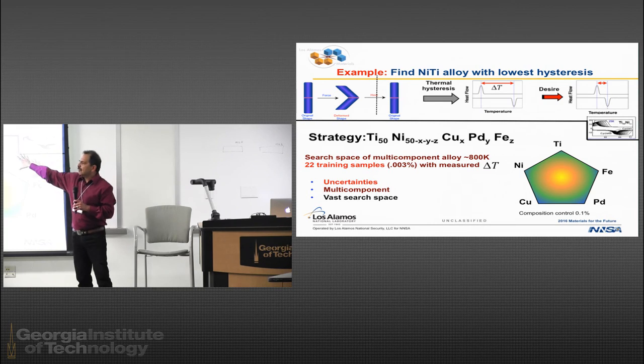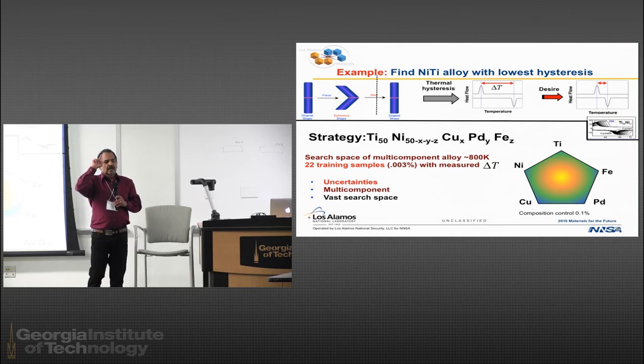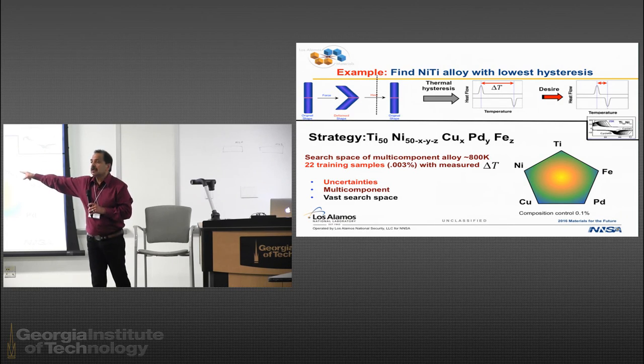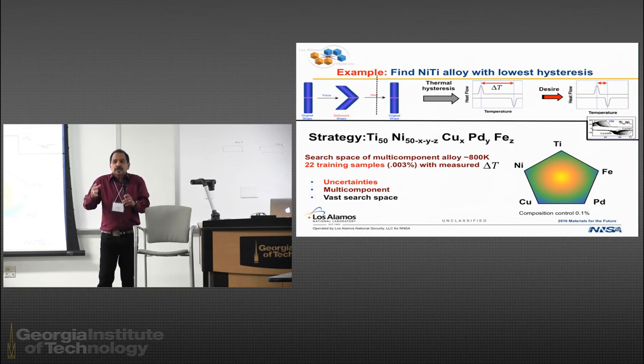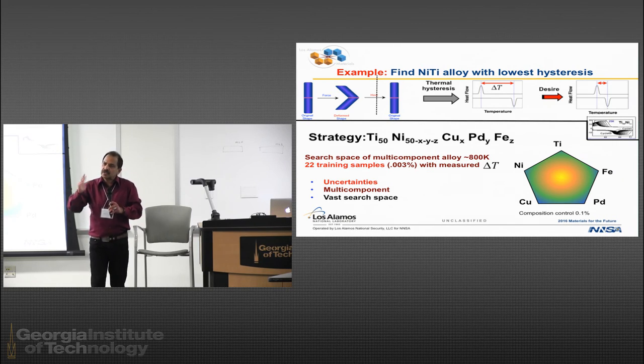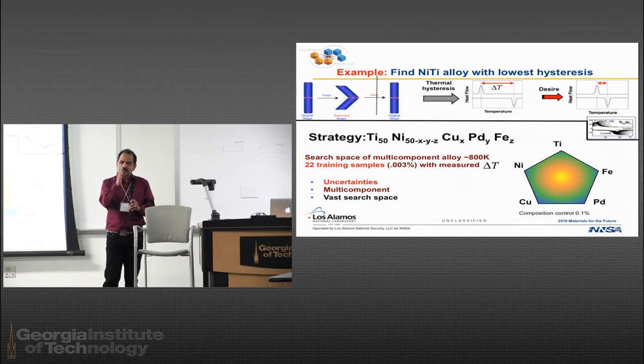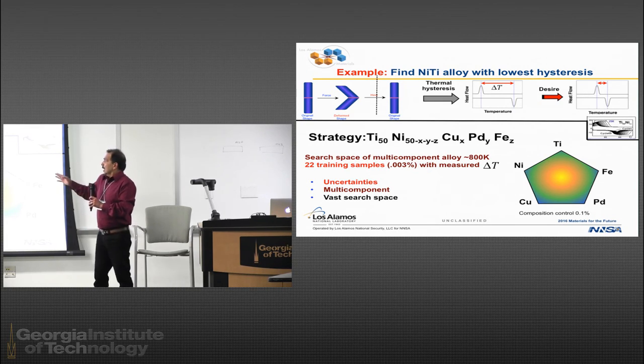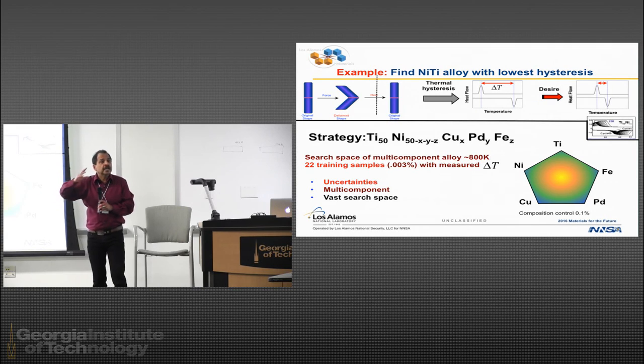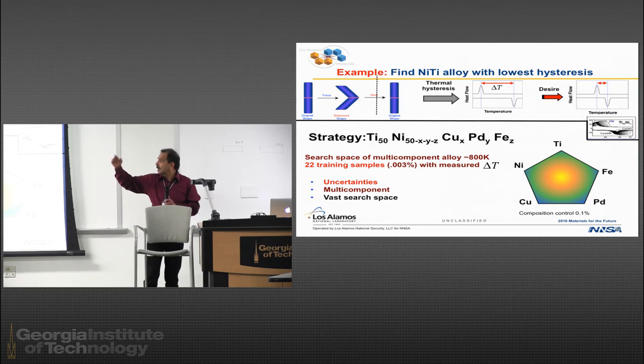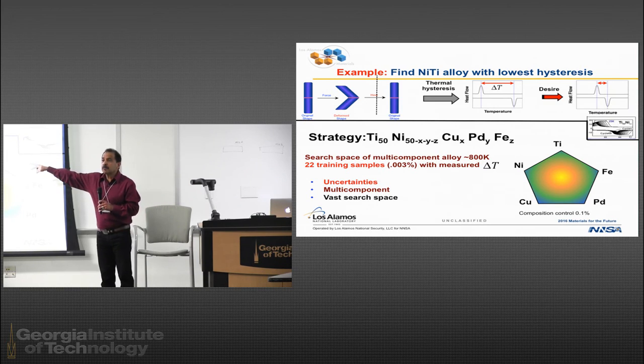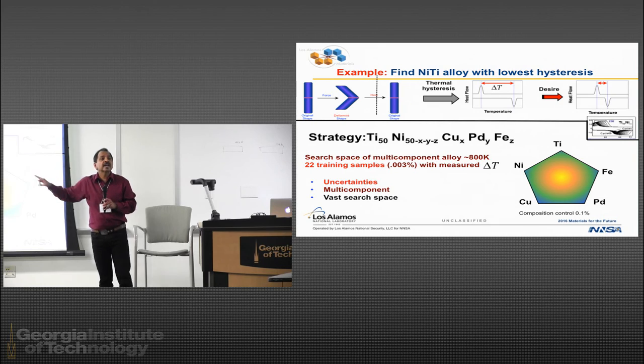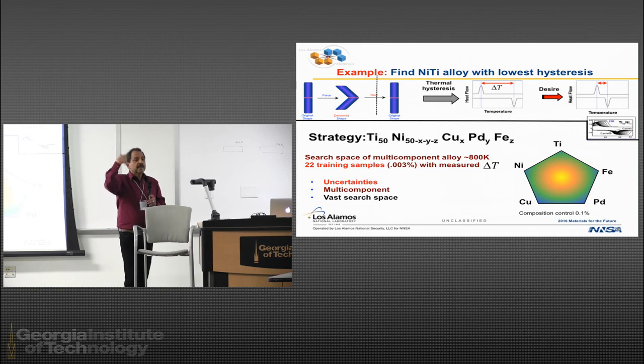Okay? So there was a lot of work done on alloys such as this with varying amounts of X, Y, and Z. So we had 22 samples, and this was already done in the literature, but we set out to do it ourselves. So we did the experiment ourselves in a very controlled fashion. The processing was really controlled. The same guys did the experiment and measured the thermal hysteresis, this delta T. Now, the problem is very simple. I want to know what X, Y, and Z will minimize the hysteresis.